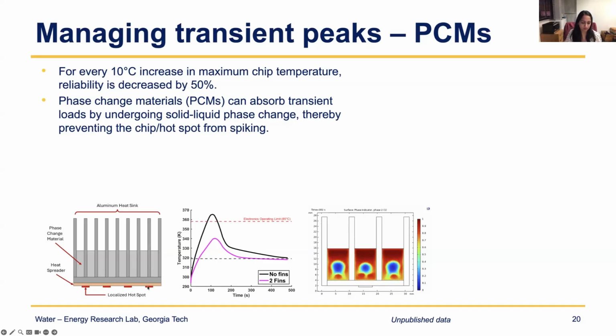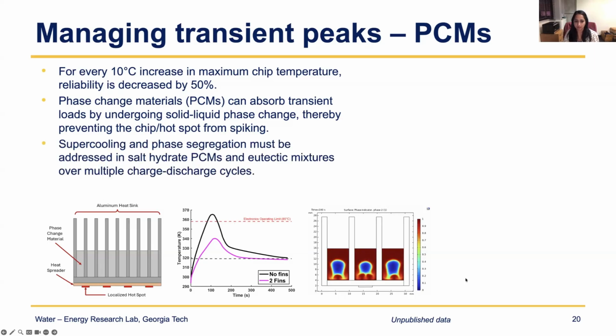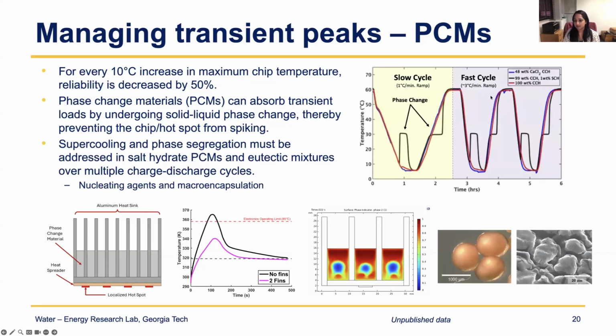So we've looked at essentially just a heat sink, a traditional aluminum heat sink with localized heat spots to simulate a hotspot on a chip. And we have some phase change material in there, and we can study how much of the phase change material is active. So how much is melting and re-solidifying under a transient spike. So within a few seconds to a minute, how is it able to absorb the heat? So we study the cycling behavior, because again, you want something that can be cycled thousands of times. So in this case, a much smaller cycling range of temperatures, because we're operating within the electronics temperatures. And you can see the sensible cooling and heating versus the latent cooling and heating. So where we have the constant temperature is indicative of the phase change happening. We can control not just the temperatures and the ramp rates, but also how quickly these cycles happen to really study how the material is responding.